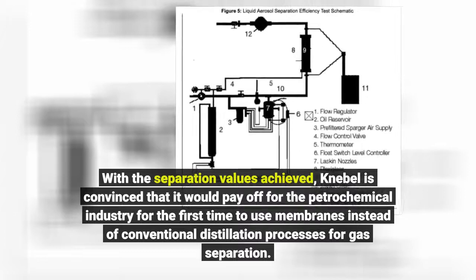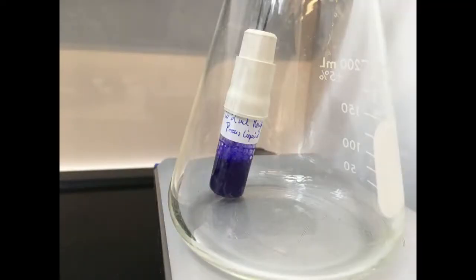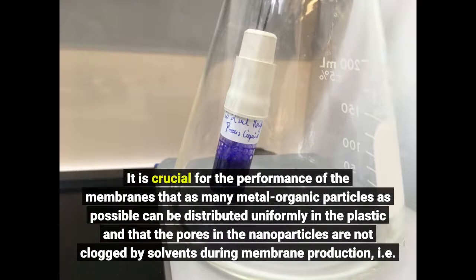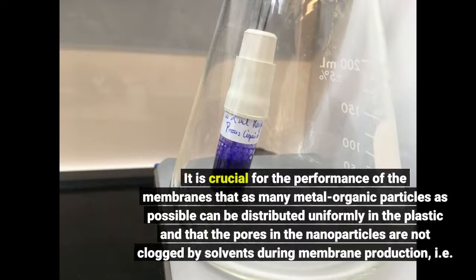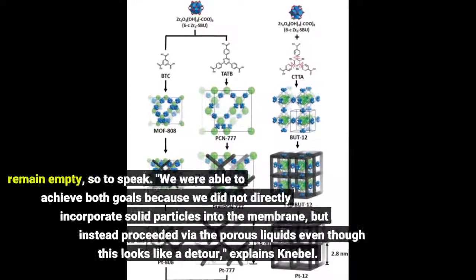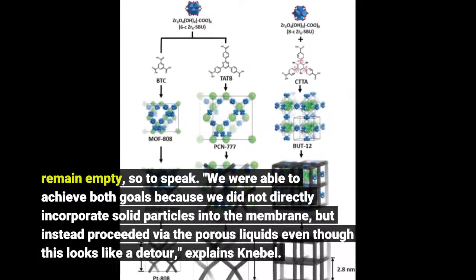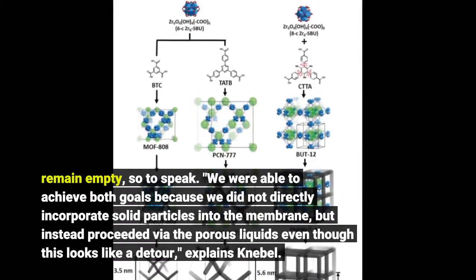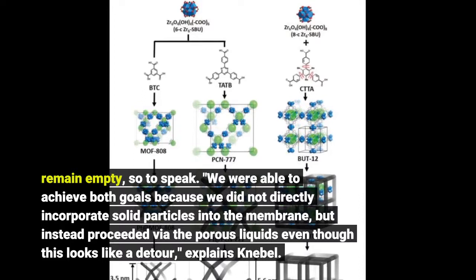It is crucial for the performance of the membranes that as many metal organic particles as possible can be distributed uniformly in the plastic and that the pores in the nanoparticles are not clogged by solvents during membrane production, i.e. remain empty, so to speak. We were able to achieve both goals because we did not directly incorporate solid particles into the membrane, but instead proceeded via the porous liquids, even though this looks like a detour, explains Knebel.